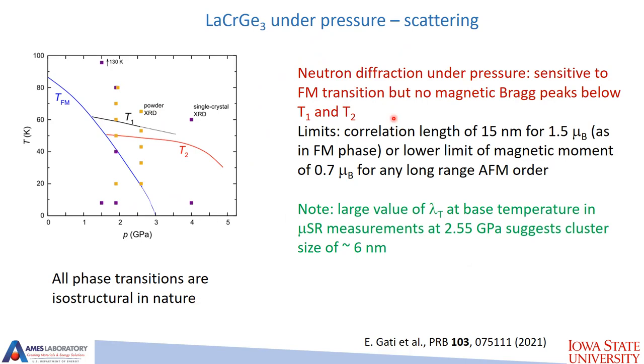So if you analyze what would be the limits to see magnetic Bragg peaks, you end up with correlation lengths of 15 nanometers if you have 1.5 μB magnetic moment, or you will not see anything if your magnetic moment is below 0.7 μB for any long-range antiferromagnet. Now, from a large value of lambda T in μSR at base temperature, this measurement suggests that the cluster size is around 6 nanometers. So it is a combination of seeing no additional Bragg peaks in neutron diffraction and a large value of lambda T in μSR measurement.